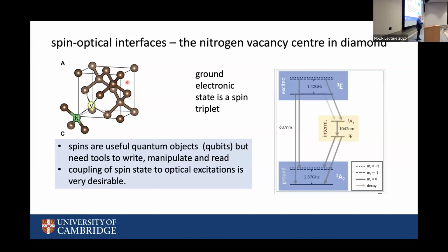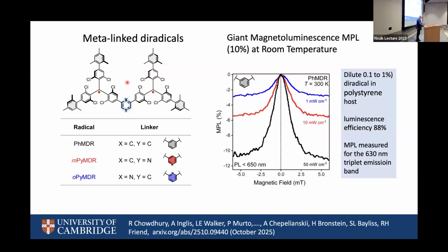And the key with the nitrogen vacancy center is the ground state triplet and a singlet, which is not seen very much, but you can set the spins of the sublevels of the triplet by optical excitation or microwave control, and it's possible to use it as an optically set, an optically read qubit. And we're starting to do similar things with our diradical. So the most recent work, which is on arXiv, lots of referees who are not very happy with it. There we go. Slightly different chemistry.